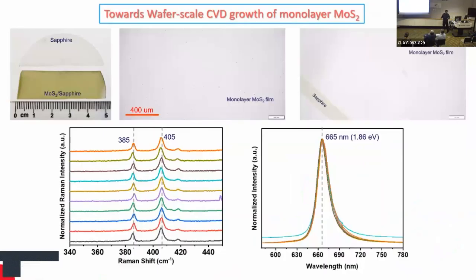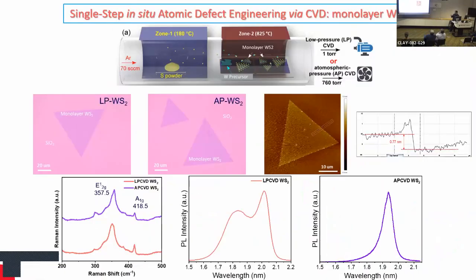We can grow MoS2 on larger areas, like wafer scale. Here you have a photograph of a half-cut sapphire wafer, and it's quite uniform over the large area. Besides MoS2, we can also grow other 2D materials like WS2. Similarly, we can use low pressure CVD growth for WS2, and we can also use atmospheric pressure based growth for WS2. Just as an example, we can have different TMDs for different applications, MoS2, WS2, and also heterostructures of these materials.